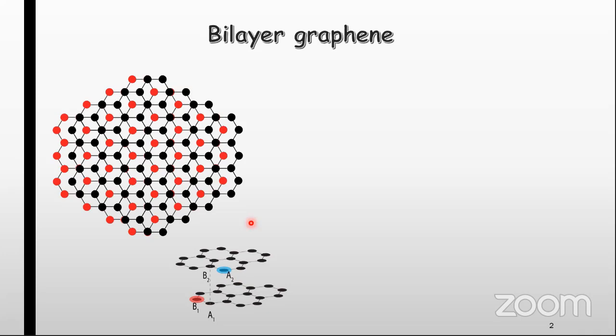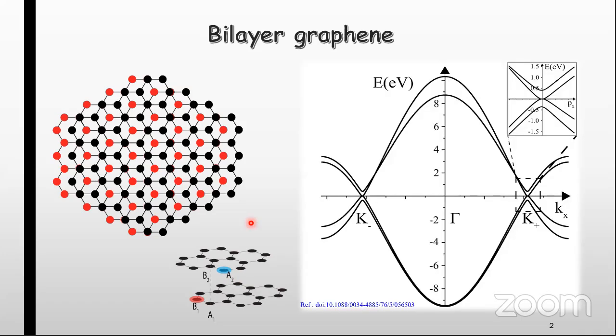If one solves the tight binding Hamiltonian, they will get this kind of band dispersion, where the points where conduction band and valence band are touching are called K points. And we can see that about this point, the dispersion is parabolic. The Fermi energy of pristine bilayer graphene will always lie near these K points. This is the only region which is accessible in the experimental limit, and these low energy bands are formed from non-dimer pair orbitals. So I will only be talking about these low energy bands.